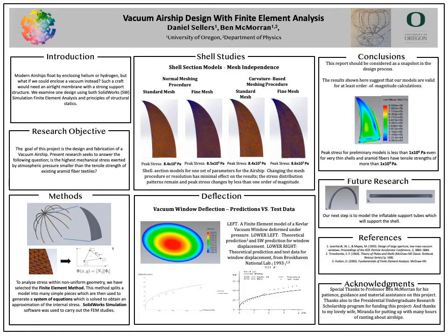Aramid fibers are best known as things like Kevlar and Zylon, which are known for their high tensile strength-to-weight ratios. We get this highly non-uniform geometry from the fabric shell under atmospheric pressure, so we elect to use the finite element method, which takes this complicated model and breaks it down into many small elements used to generate a system of equations, or sparse matrix equation. This system of equations can be solved to give an approximation for the stress within the fabric shell, and we use SOLIDWORKS simulation software, a commercially available software for carrying out finite element method studies.